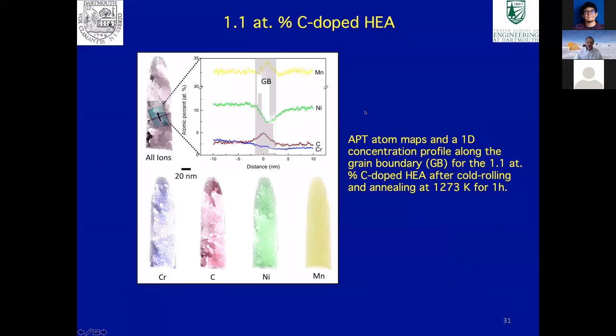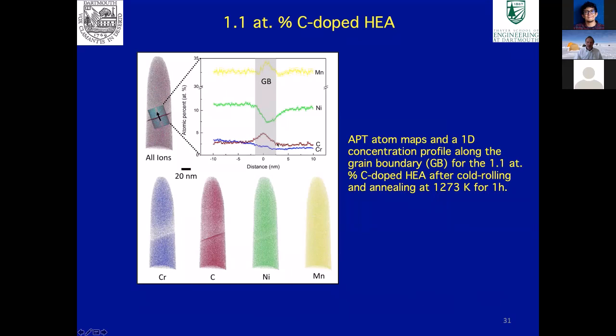Using atom probe tomography again, we looked at the grain boundaries, and what you find is after this recrystallization processing, we've got an increase in manganese at the grain boundaries, a decrease in nickel, and an increase in carbon at the boundaries here. And you can actually see this on some of the images themselves, where we've got excess carbon.